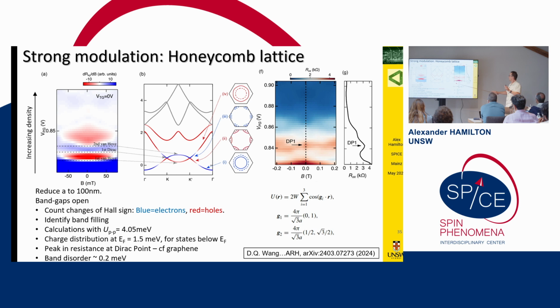So I think what's nice about this is if we believe this, and I have no reason not to, we've taken ordinary electrons in gallium arsenide, which is a zinc blende cubic crystal, and we've imposed a triangular lattice. So we've got a completely different lattice symmetry. We've changed the electrons from being electrons into holes. We've changed them from being massive electrons to massless Dirac particles. I think that's kind of nice.